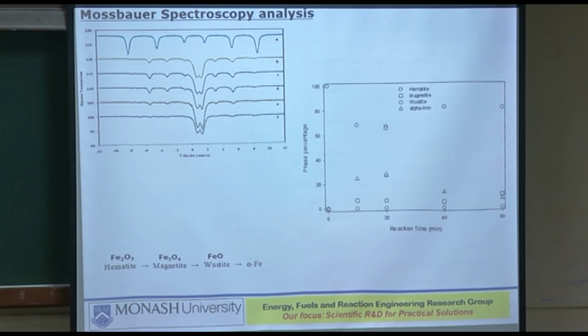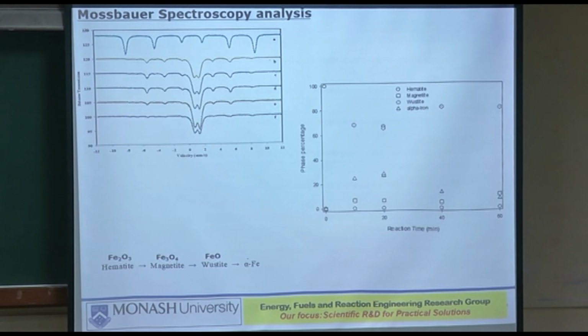From the analysis of the spectra, it gives you the Fe2, Fe3 ratio. Okay. So Mossbauer spectroscopy is done on a large amount of sample, so that you can actually see in the large amount of sample how much transformation has occurred, as opposed to X-ray diffraction, where you can see it only for a tiny amount of sample. But across the whole range of samples, whether the reduction has taken place or not can be determined better by Mossbauer spectroscopy. So there, what you can do is exactly the same thing.